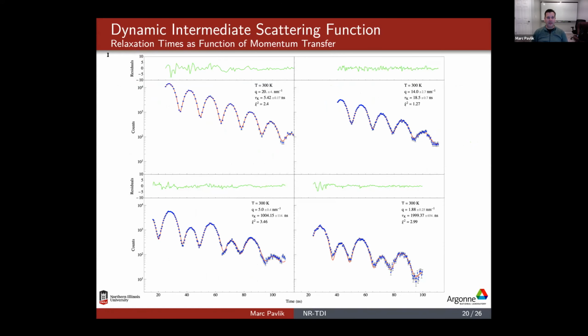So here, for example, I'm using different momentum transfers. I have 20 inverse nanometers, 14 inverse nanometers, 5 and 2. What we're doing is zooming in and out of our molecule. Here at 20 inverse nanometers, I'm zooming in more on probably the individual molecule itself, which is why I see this fast beating pattern. Whereas as I start to zoom out, I'm looking more at a group of particles, and you can see that my relaxation rate is decreasing as I move out.